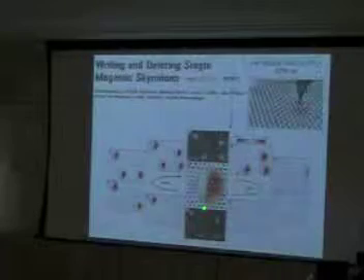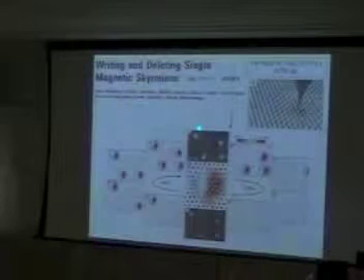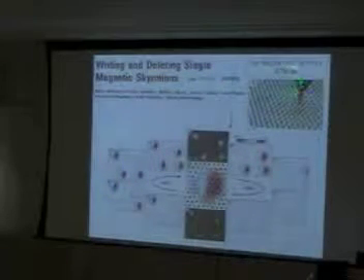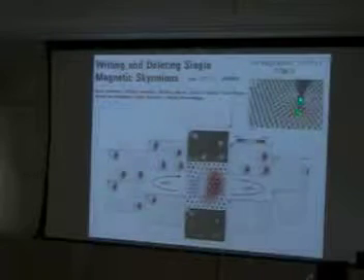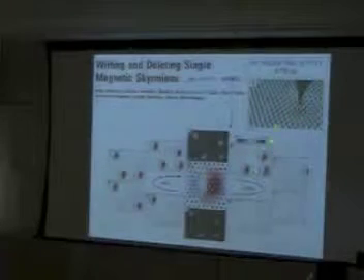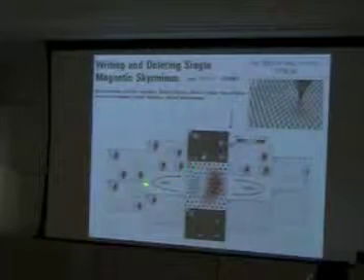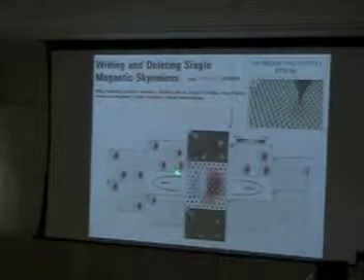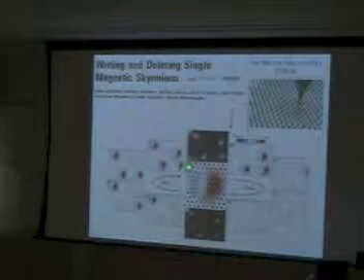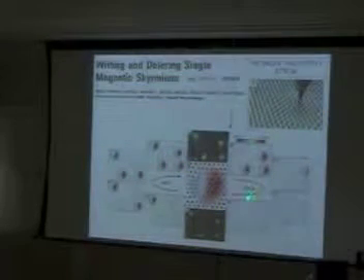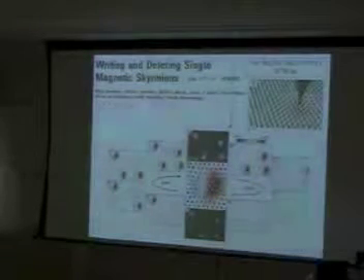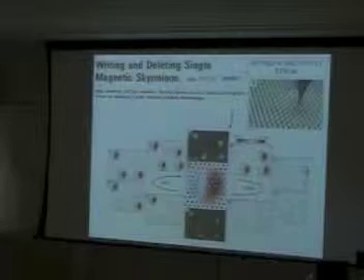In fact, there are already experimental results in the group of Wiesendanger in Hamburg, where in a layer of palladium on iridium, by sending an electrical current from the tip of the STM, they are able either to write a bubble at some points, or, by changing the conditions, changing the field, to delete this bubble. So there are already experimental examples of this sort of creation and annihilation.